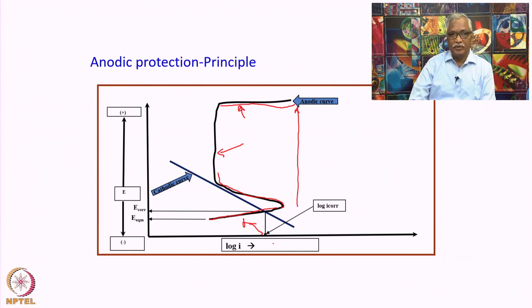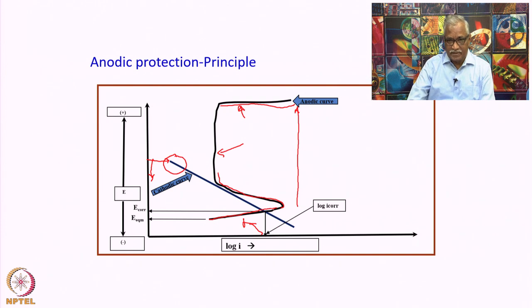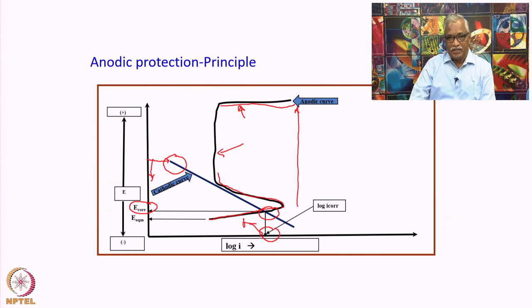If you immerse this metal in an acidic solution or any corrosive medium, it attains a corrosion potential defined by cathodic kinetics. The equilibrium potential for the cathodic reaction, as it polarizes towards more negative potentials, causes the current to increase. At the point where the cathodic current density equals the anodic current density, the metal exhibits a potential called E_corr, with a corresponding corrosion current density I_corr.